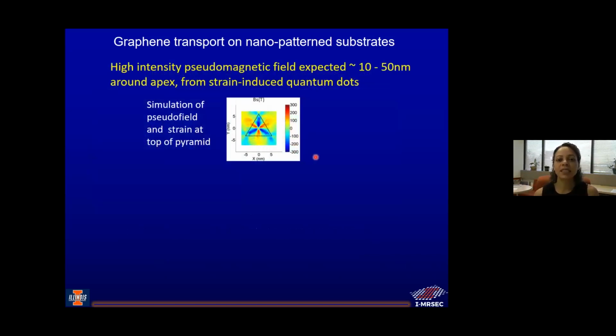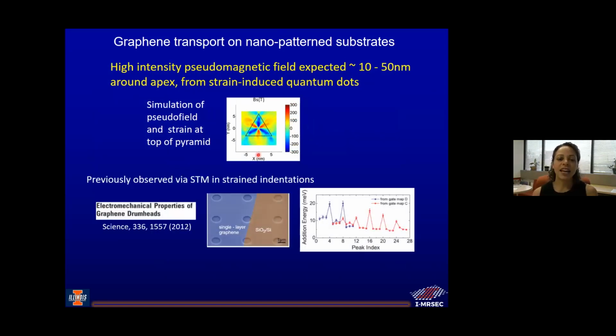And so we expect to see from these 10 to 50 nanometer dots around the apex a very high intensity pseudo-magnetic field. And in fact, this had been previously observed, but locally with STM probes in graphene on a drumhead. So in this case, it was strained by being pinned around a hole. Okay, but when they pinned the graphene around a hole, again, they saw these very high pseudo-magnetic fields. So we would expect something similar in our devices. And we believe that that's leading to some of the confinement.